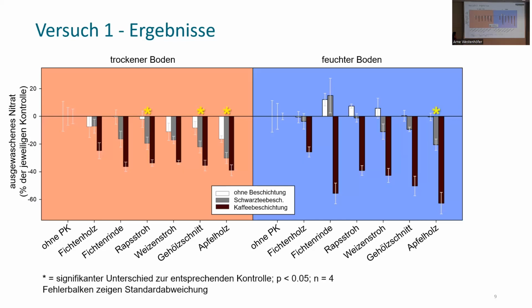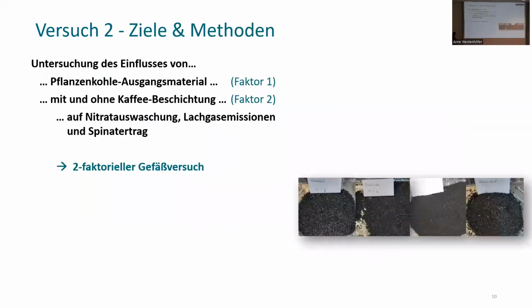There hasn't always been a positive effect on nitrate leaching. But then we carried out this variance analysis and found out which ones are random effects and which ones are statistically significant. You could say, well, this is a value that is solid. We see that with black tea coating in dry soil, there is a reduction of nitrate leaching, and in the wet soil or moist soil, only in one variant. If I do it with coffee grounds, it looks much nicer, particularly in a moist soil. The use of coffee ground coated biochar always led to reduced nitrate leaching. So this is why in a second trial, we are only using coffee ground coating anymore, because that's most beneficial.